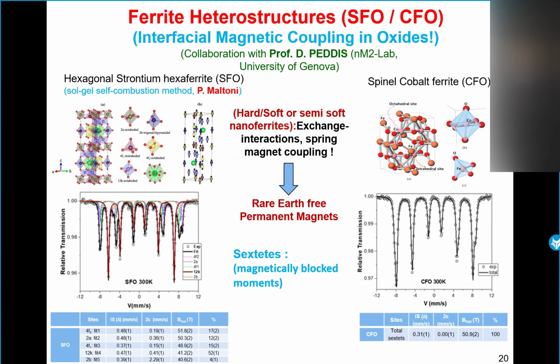So it's an interesting system because it is an alternative for permanent magnets. It is interesting for rare-earth-free permanent magnets because in hard-soft nanoferrites, we have the possibility to have exchange interactions, interfacial exchange interactions, or spring magnet coupling. So that may allow us to make a permanent magnet without rare earth material.